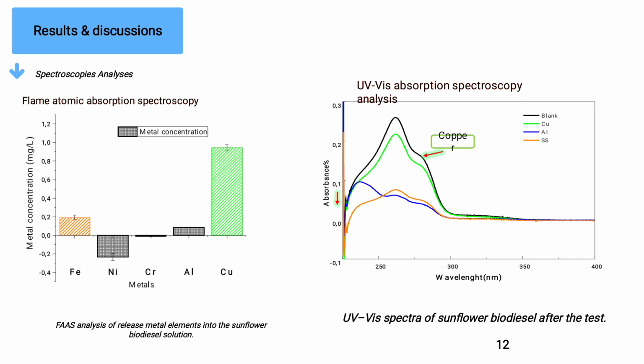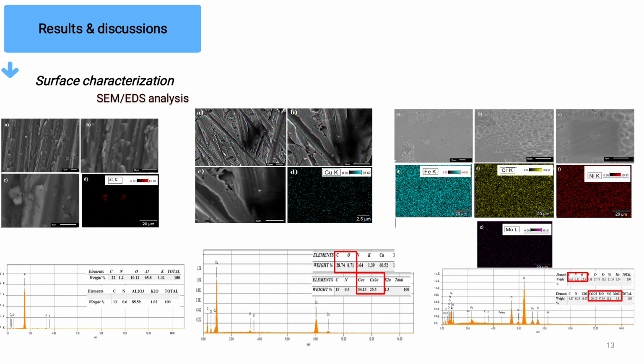The FAAS analysis confirmed the higher copper release compared to aluminum and stainless steel, with nickel and chromium below the detection limit, indicating a protective oxide layer formed on the surface of the metal. The ultraviolet-visible detects significant copper oxidation, while stainless steel and aluminum showed minimal oxidation. The surface characterization by the SEM analysis revealed the following key findings.